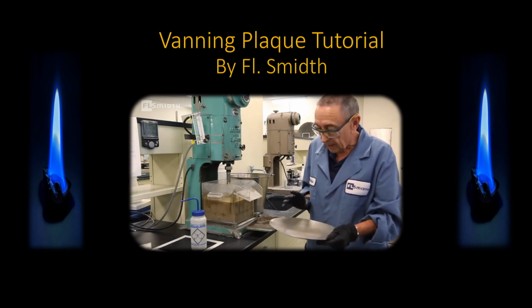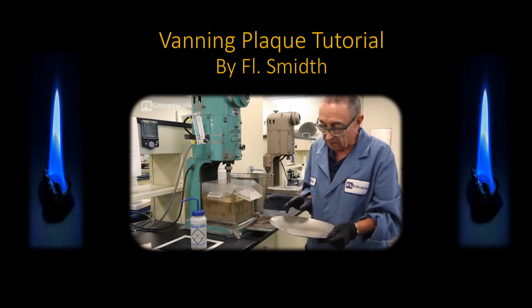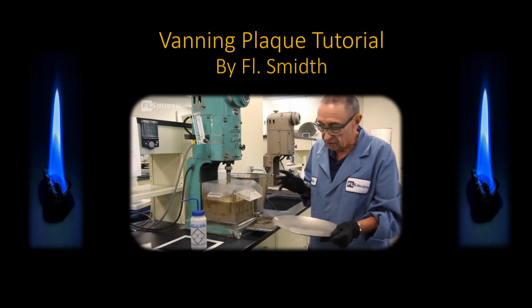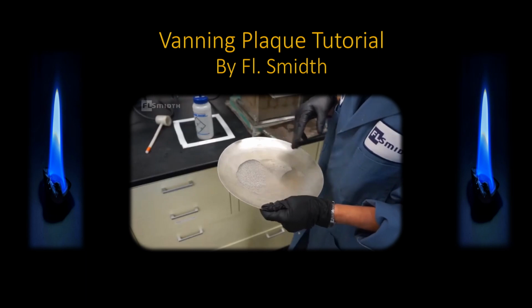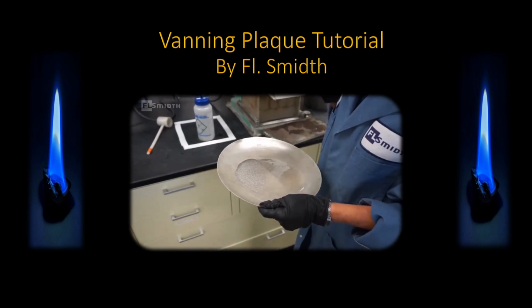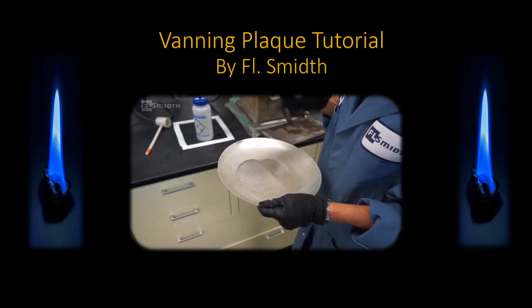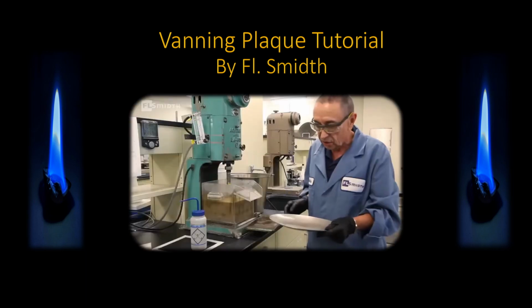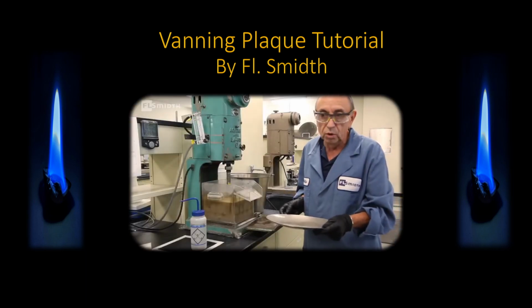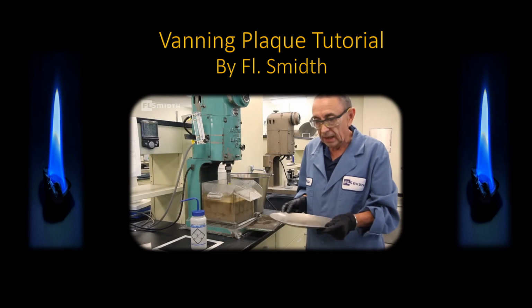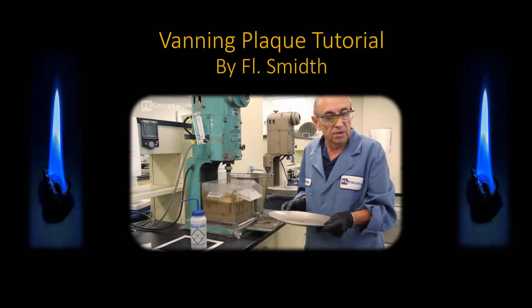Occasionally, if you're looking at a concentrate sample that has reagents added, you'll form a froth on top. You can break this froth up by spraying it with a solution that's half a gram per liter Cytec Aero Dry 100 or some similar surfactant.